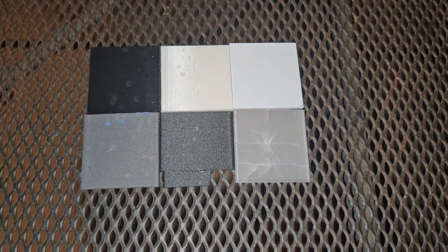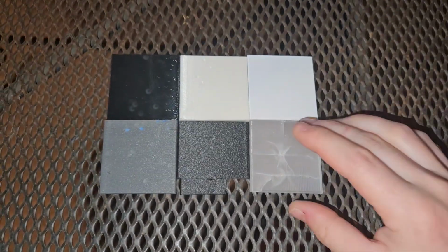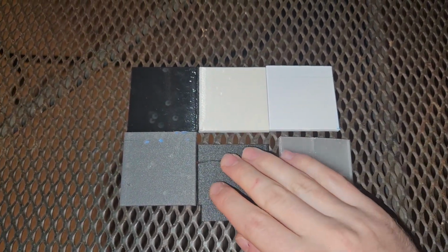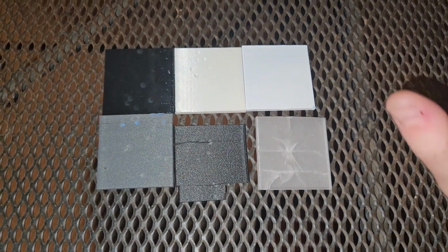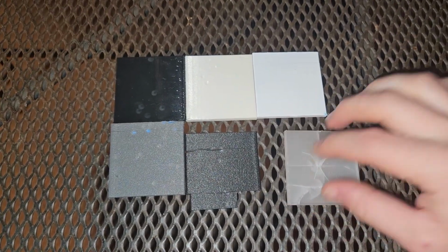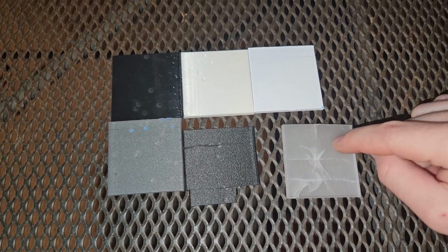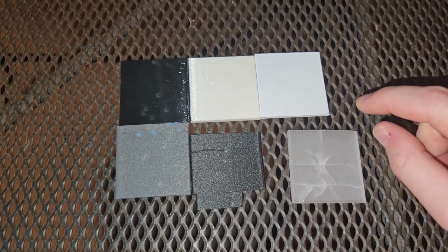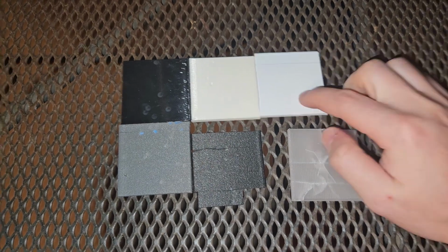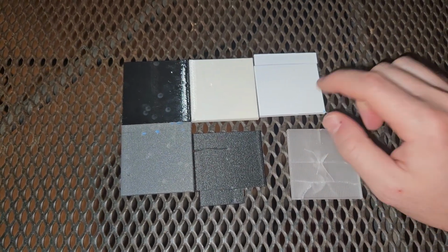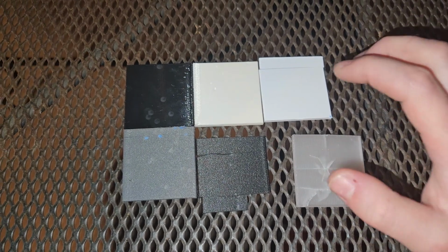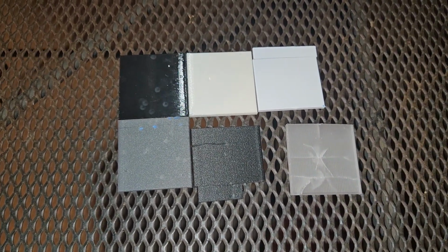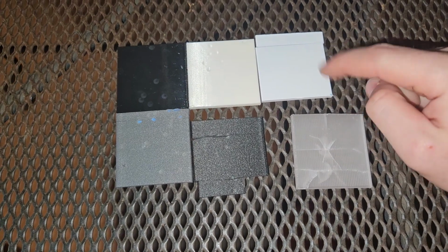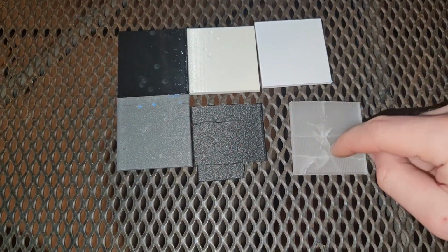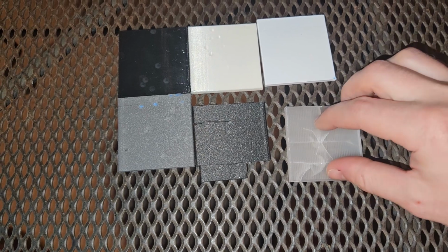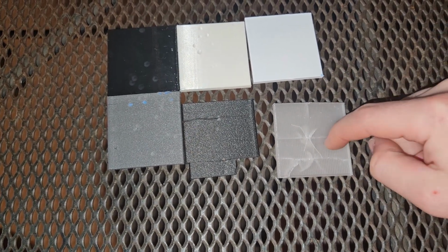Let's talk about the indisputable losers of this test. And that would be the PETG and the polycarbonate. Again, that does not mean these are bad materials. PETG is a super useful material. It prints really nice like PLA, but it has the thermal threshold where you're not going to melt in the sun. I know some people don't like to believe that PLA can melt in the sun, but it has happened to me multiple times. You can absolutely melt your PLA just being outside. Out in the Southwest, it's pretty hot, so it really is an issue. But for now, PETG, yeah, it has good thermal properties, but it is clearly pretty brittle.